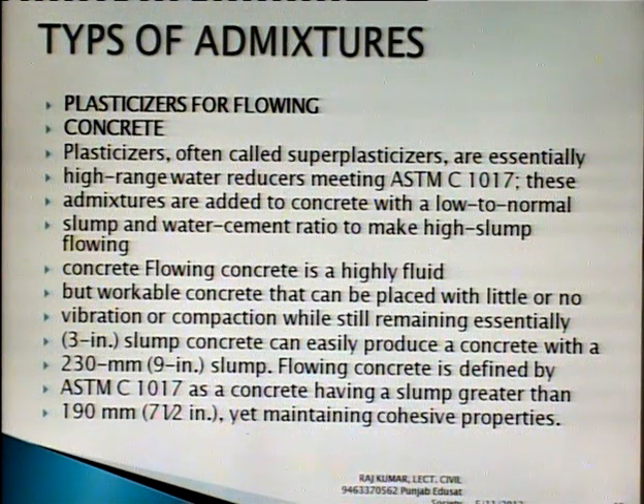Plasticizers, often called superplasticizers, are essentially high range water reducers meeting ASTM C1017. These admixtures are added to concrete with a low to normal slump and water cement ratio to make a high slump flowing concrete. Flowing concrete is highly fluid but workable concrete that can be placed with little or no vibration, while still remaining cohesive. Concrete can easily be produced with a 9-inch slump. Flowing concrete is defined by ASTM C1017 as concrete having a slump greater than 7.5 inches, yet maintaining